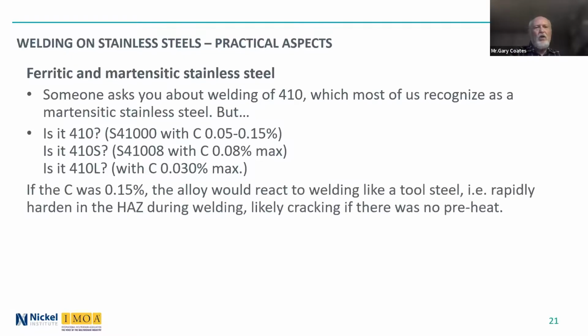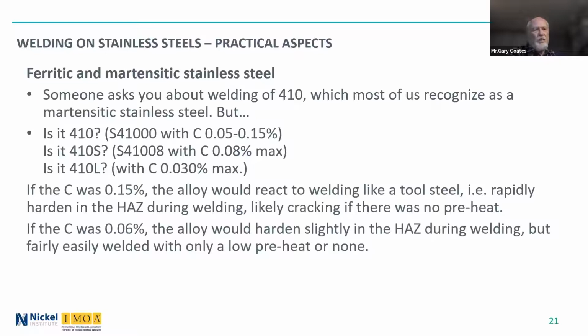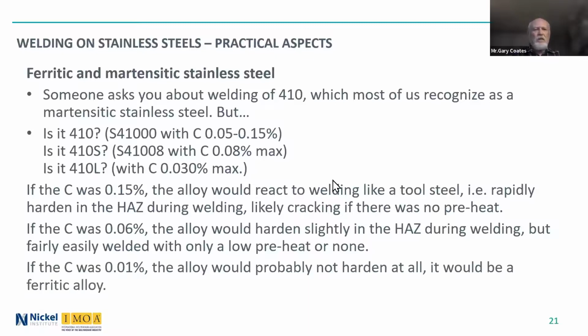Now, if we had 0.15% carbon, the alloy would react to welding like a tool steel. In other words, it would rapidly harden in the heat affected zone during welding and be likely to crack if there was no preheat. If it was the S grade and let's say had 0.06% carbon, the alloy would harden slightly in the heat affected zone, fairly easily welded, usually a low preheat, and if it's thin enough, maybe no preheat at all. If you didn't have the preheat on thicker material, it could crack, but that's only on thicker material. And if the carbon content was 0.01%, the alloy wouldn't harden at all.